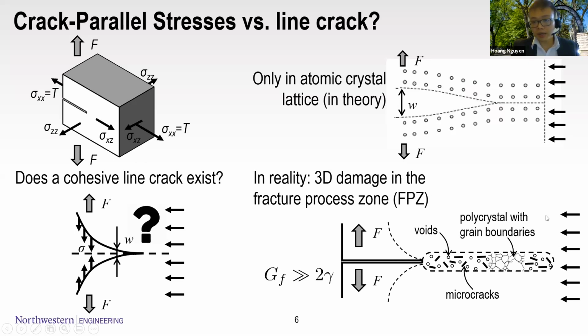And in another scenario, for example in metal, you have polycrystals or grain boundaries forming, depending on how and at what temperature you create or fabricate the metal structure. It can also interact with the crack parallel stress and cause some deviation from the conventional theory. And in this case, we may see some change in the GF, which is the fracture energy, and it can cause a deviation from the surface energy, the pure surface energy.